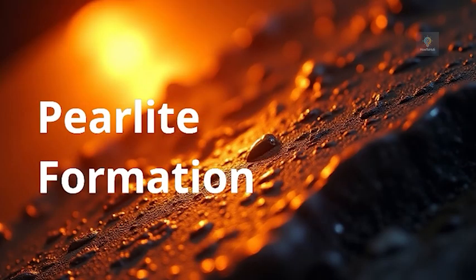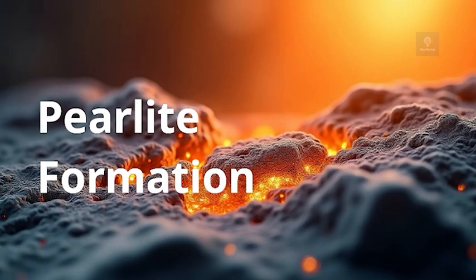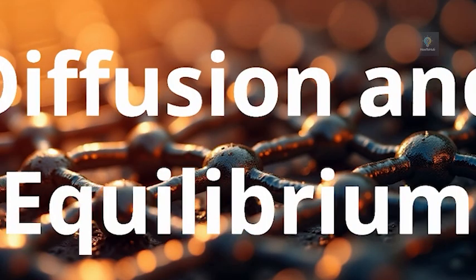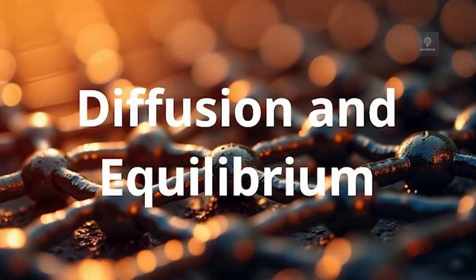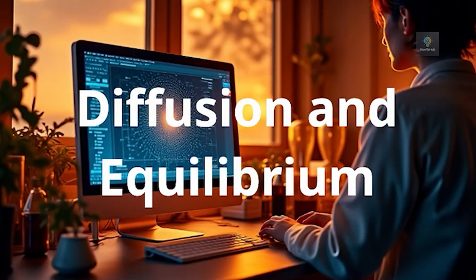In steels with less carbon, hypoeutectoid steels, some ferrite forms before reaching the eutectoid temperature. The final microstructure becomes a mix of proeutectoid ferrite and pearlite. In steels with more carbon, hypereutectoid steels, cementite forms first as austenite cools. At the eutectoid temperature, remaining austenite transforms into pearlite, creating a mix of proeutectoid cementite and pearlite. Time and temperature, the TTT diagram. All these transformations rely on diffusion, the movement of carbon and iron atoms through the lattice to form new phases.